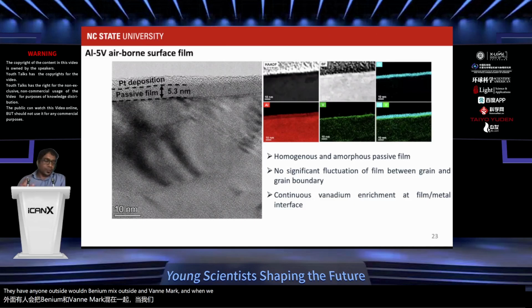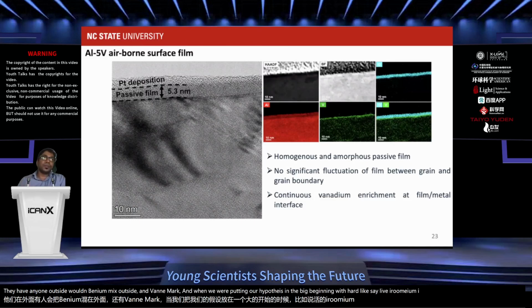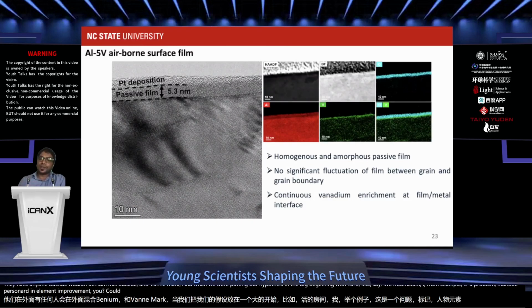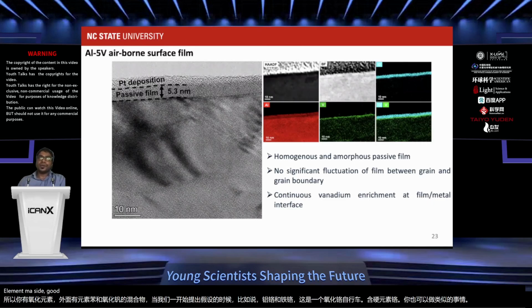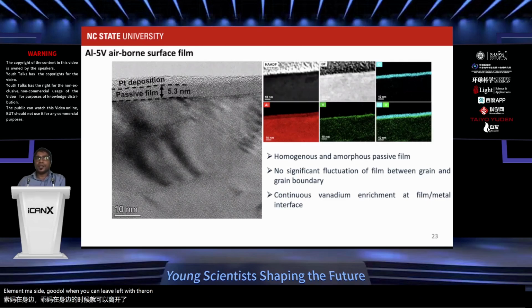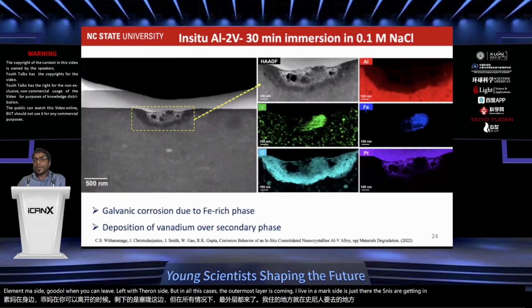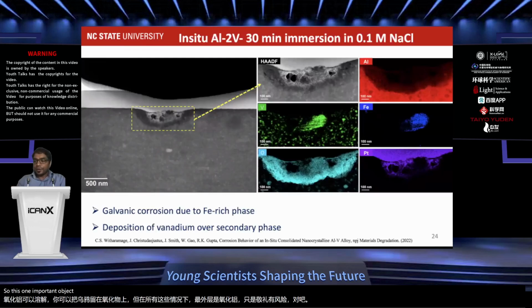And when we were putting our hypothesis in the beginning, we thought, say, in the aluminum chromium, iron chromium example, there is a chromium oxide passive film. We thought in aluminum chromium, you could do a similar thing. Aluminum oxide could dissolve and you can be left with the chromium oxide. But in all these cases, the outermost layer is aluminum oxide. It's just that the solutes are getting enriched, right? So that's one important observation we had.